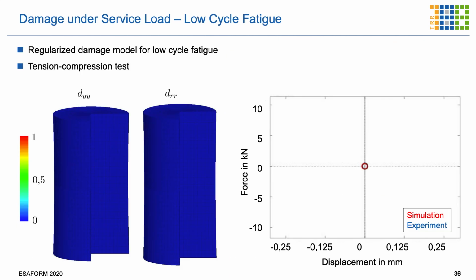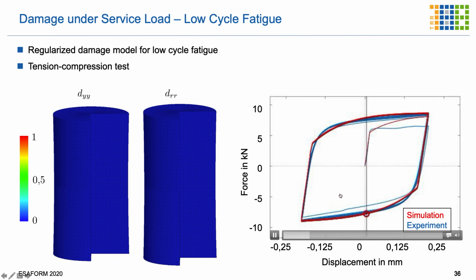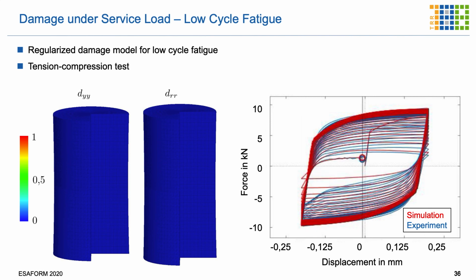So a final example from the computational side before I end my talk is related to the low cycle fatigue. So our models for low cycle fatigue are shown here, and what we see here is in case of low cycle fatigue, our simulation and our modeling is both supplying an excellent comparison and predicting the effect of damage on the low cycle fatigue.